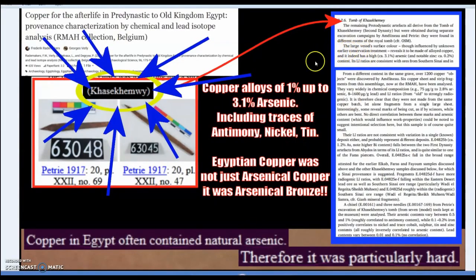We go back to Khasekhemwy. Copper alloys of above 1%, so 1.1, 1.2, up to 3.1% arsenic. Includes traces of antimony, nickel and tin. Antimony bronze is another form of copper alloy which makes it much harder and is still used now, for instance, in places where sparks and igniting materials might be a problem. The workers will use a bronze hammer, which is usually antimony mixed in there as well, or nickel. But Egyptian copper was not just arsenical copper; it was arsenical bronze, as in the Tomb of Khasekhemwy.